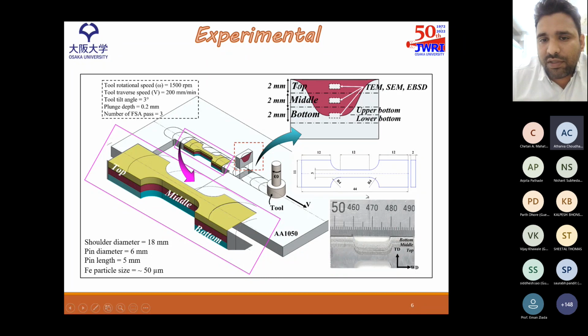So this is the top layer, which starts at the top and ends at 2 millimeter. Then there is a middle layer and then a bottom layer. We have observed a bimodal distribution of particles as well as grains in the upper and lower part of the bottom layer. So we have further classified it into the upper bottom and the lower bottom section. Here we have used a shoulder diameter of 18 millimeter. It means the processing zone is 18 millimeter, and the particles are mainly reinforced in the zone of 6 millimeter because that is the pin diameter. So we call it the stir zone.